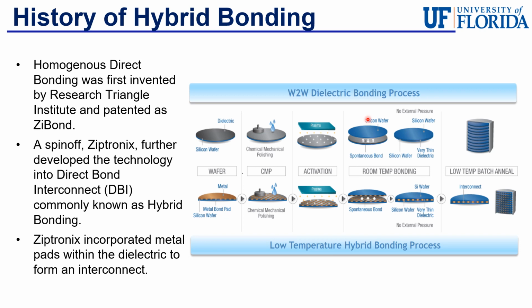Now, what Ziptronics did is they incorporated these small metal pads within the dielectric layer that could be aligned and bonded through an annealing step after the spontaneous bond had been formed between the oxides. Ultimately, this would form conductive connection paths between the two wafers.